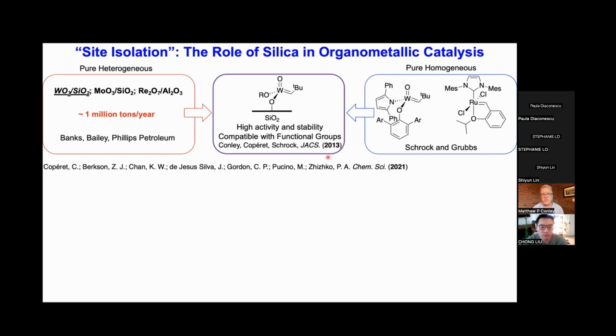So really the whole crux of this chemistry is, if you want to improve the properties of those catalysts, just incorporate a well-defined site by reacting it with silica to make some congener that would be similar to what you feel is an intermediate for the tungsten oxide on silica material. So that's something we did in my postdoc as well. This catalyst is quite active. It's Z-selective for olefin metathesis. You put it onto silica or a related dialkoxide onto silica, it becomes significantly more active because you're sort of opening up the steric environment of the tungsten, because the silanols on silica, though you're on a bulky object, they behave like small ligands.